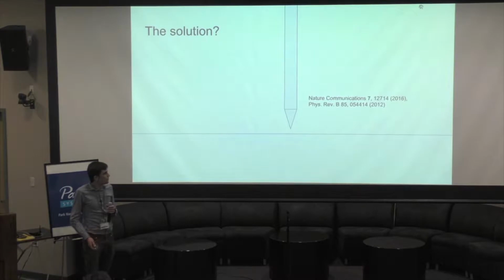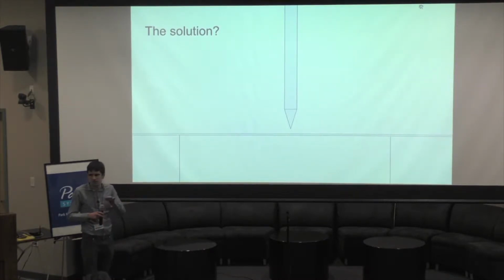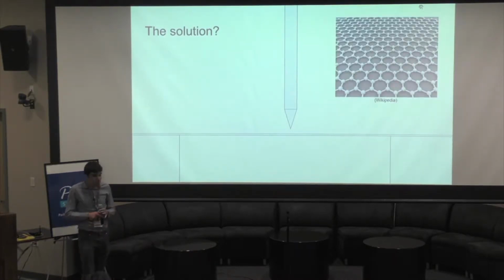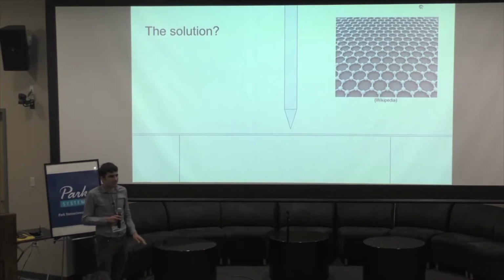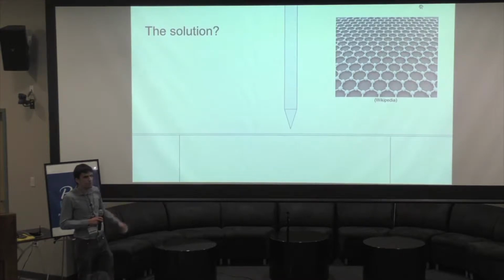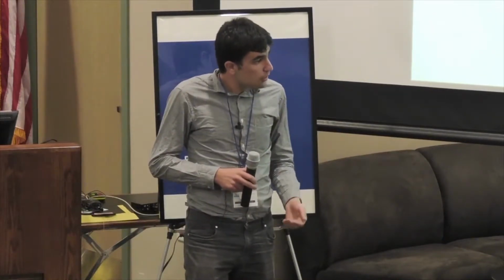And the other option is to reduce the size of the surface that this tip scans over by making it thinner. One potential solution to that, as with most other problems in nanotechnology, is the use of graphene. It's extremely thin, with good mechanical properties and electrical conductivity, which could screen out other electric fluctuations. The idea is to use a suspended graphene sample stage for magnetic resonance force microscopy. So the goal of the project that I've been working on is to try to characterize that non-contact friction and see whether this would work.